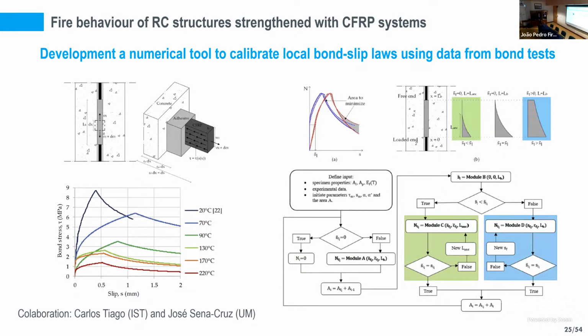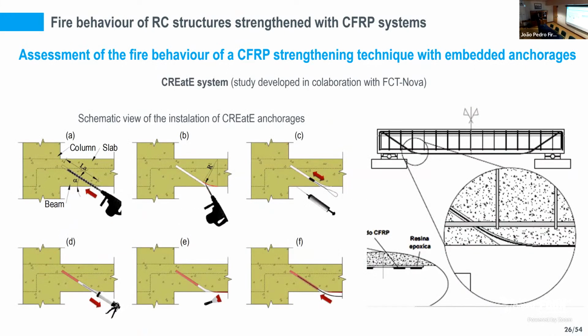We were also able to develop a numerical tool that uses the experimental data from the bond tests to calibrate local bond-slip laws in a much more automatic and optimized way than the way I did in my PhD. So this was also an additional development on this topic. And we also assessed the fire behavior of different variants of CFRP strengthening systems. Here I show one of these systems that we assessed, a system which is basically anchoring the CFRP laminates into holes that are drilled at the anchored zones of the CFRP system, so close to the supports, providing a better anchorage capacity to the CFRP system.